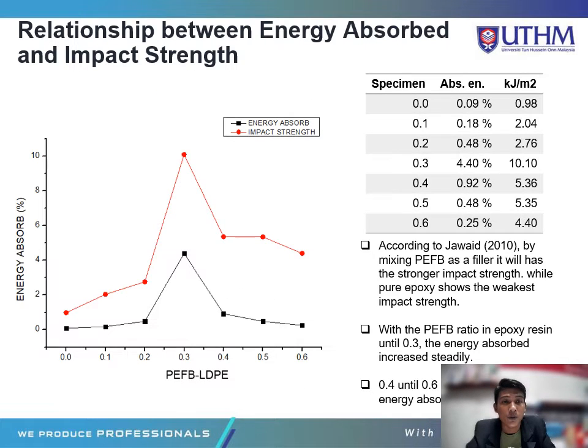This graph shows the relationship between energy absorbed and impact strength test. As you can see, the dotted red line shows the impact strength, while the black dotted line is energy absorbed. For specimen 0.0, the energy absorbed is 0.09% and the impact strength is 0.98. For the 0.1 sample, the energy absorbed is 0.18% while the impact strength is 2.04. For sample 0.2, the energy absorbed is 0.48% while the impact strength is 2.76.